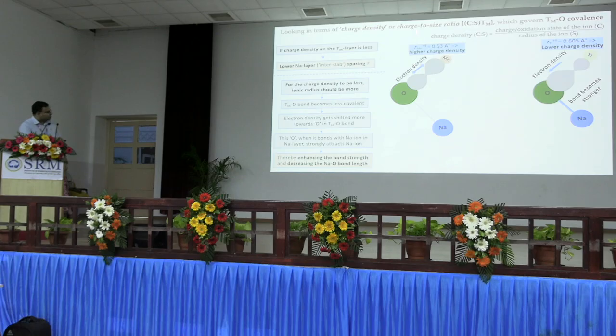Now, what can we do to try and address this? If we look at the structure of the layered sodium transition metal oxide, I will come back to this point again. It's beautiful in the sense that it is the same oxygen ion which on one side is bonded to a sodium ion, making a highly ionic bond, and on the other side the same oxygen ion is bonded to a transition metal ion, making an ionocovalent bond.